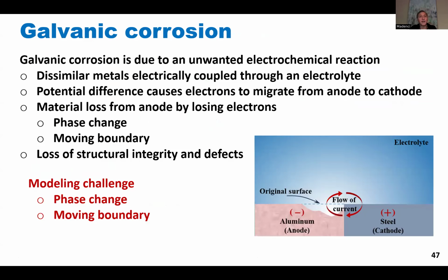Okay, so then the other problem that I considered here is where you have phase change, a moving boundary. The first problem I showed you, multiphysics, has crack initiation and crack growth, which is challenging because of the singularities that you may face. Now here, if you have, let's say, galvanic corrosion, you're going to have material loss from the anode. Electrons are going to be lost from the anode, and you're going to have a phase change. This aluminum is going to become electrolyte, and then you have this moving boundary here.